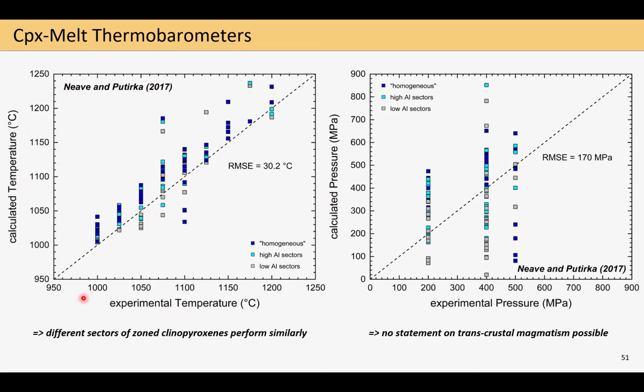And here I'm only showing you now the results for the relatively recent Neave and Putirka algorithm, which was among the best performing ones I explored. And for temperature, I think we can see a more or less okay-ish result. So the thermometer seems to work, so we can use it. And an interesting thing here is that several of my clinopyroxenes show some sector zonation in alumina. And although both sectors seem to more or less perform equally well for the temperature, it seems that I cannot currently use such models or formulations to make more statements about which of these two sectors is really the true equilibrium composition, or if even one of them is in equilibrium.